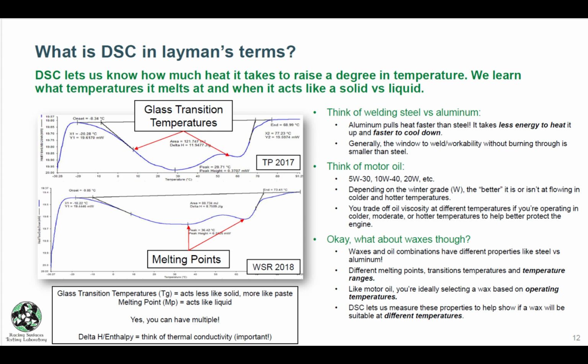So, looking at this curve here, we can clearly see where the melting points are. And through a quick calculation, we can even determine where the temperatures are for the glass transition. I want you to notice here that we actually have two melting points for both. This was Turfway Park in 2017, and this was Windstar from 2018, before they switched back to dirt themselves. You can see that we have two peaks here. That means we have two melting points of this wax. What we're looking at is one melting point of the short chain fibers, and then another melting point of those longer chain fibers. And these characteristics are what's really going to give some of these tracks their performance in colder versus hotter conditions.